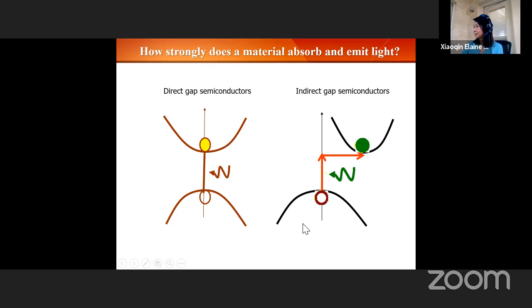In an indirect semiconductor, the top of what we call the valence band is misaligned with the bottom of the conduction band. So if you excite the material using what we call off resonance, or a photon that's well above the band gap, there's a very rapid relaxation of the electron to the bottom of the conduction band and the hole to the top of the valence band. And they have mismatched momentum. For light emission to happen, it has to involve a phonon to satisfy the momentum conservation. As a result, indirect semiconductors are not efficient light emitters. The most famous example, of course, is silicon.